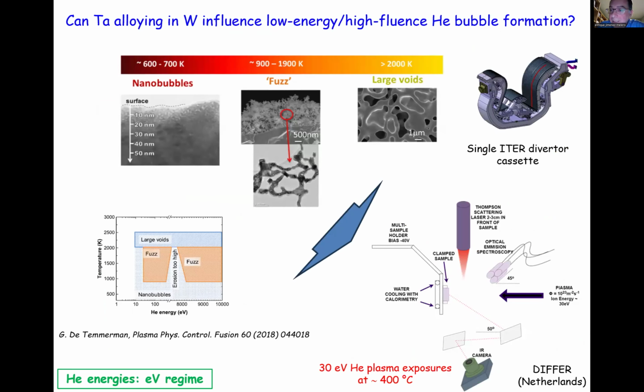Now, we're going to have helium, especially helium with different energies. So it's going to be helium from the plasma at electron volts or kiloelectron volts. We are going to form also helium inside the material as well, in the bulk, not at the surface, but inside the material. If we look first at the helium with low energies that comes from the plasma, depending on the temperature and flux and fluence, then we can form, very close to the surface, a few nanometers, what's called nanobubbles. And if it is a relatively high temperature or higher, then we call these fuzz structures and large voids. And as you can imagine, this is not good for the integrity of those components.